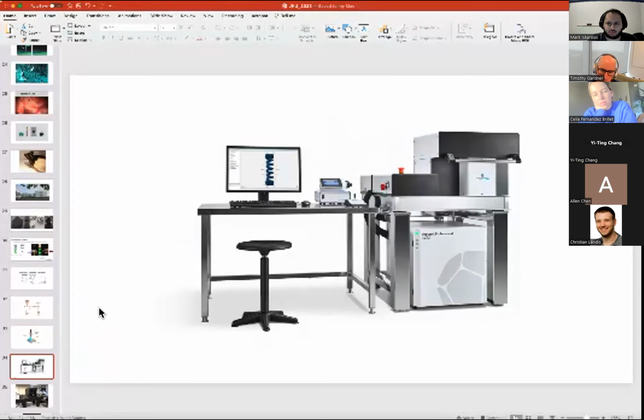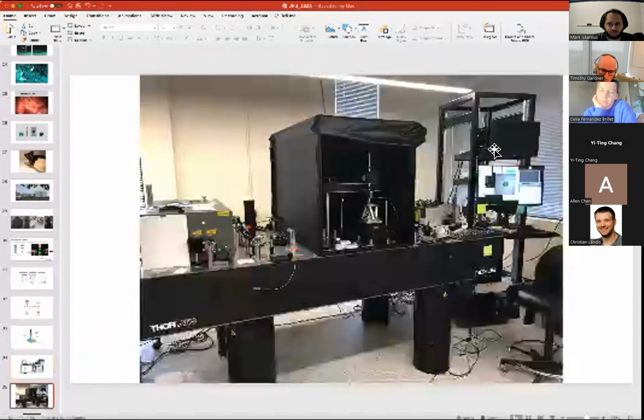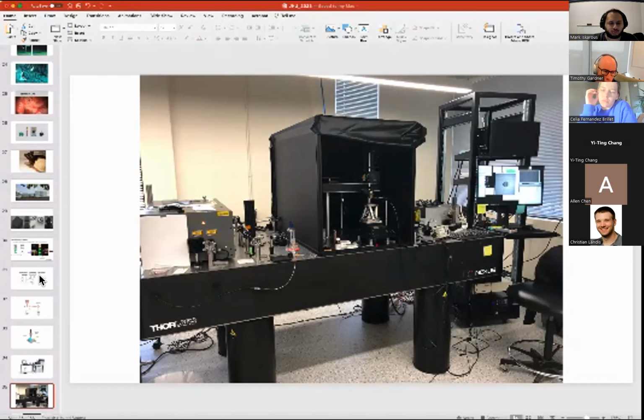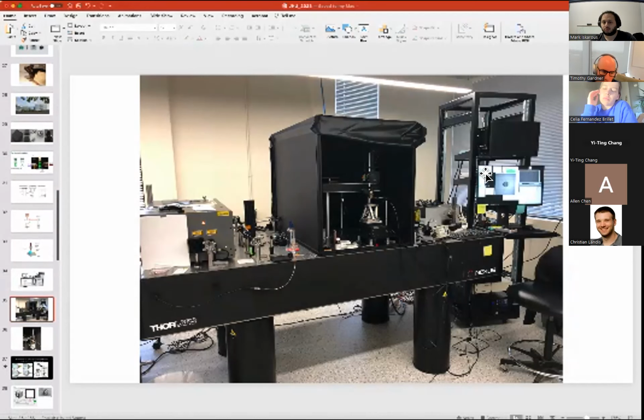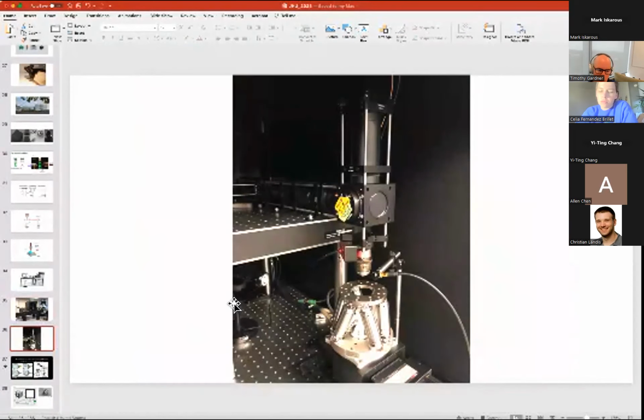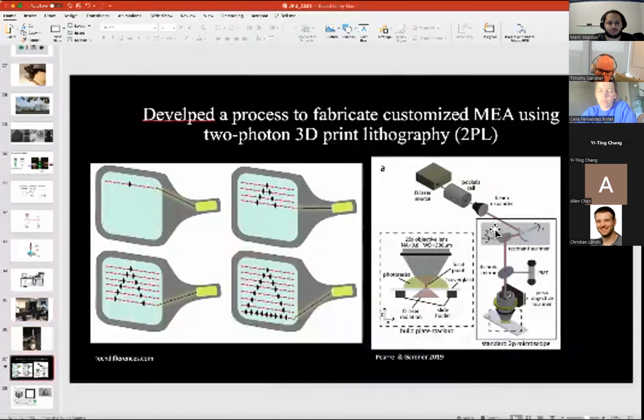The approach that we took to fabricating in this two-photon space was to modify a two-photon microscope with a resonance scanning mirror so that we could do printing on a faster time scale. And it's essentially just a two-photon microscope running ScanImage, which is that open source software that some of you may have used for two-photon imaging. And we made a plugin that goes into ScanImage that basically converts any two-photon microscope into a 3D printer. And what's pretty cool about that is the standard two-photon microscopes these days include resonance scanners, and those can be typically 8 kilohertz, sometimes up to 20 kilohertz for some of the fastest ones these days.